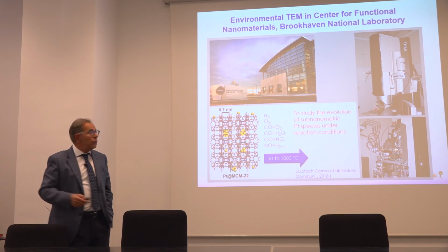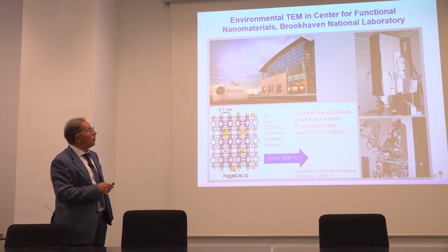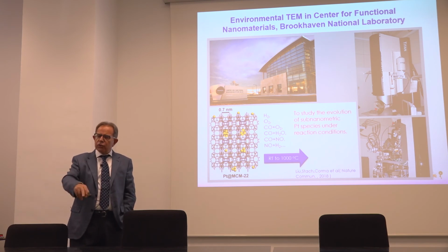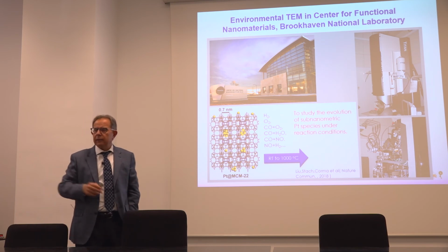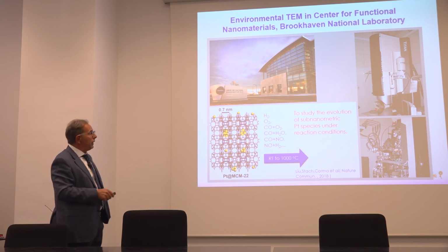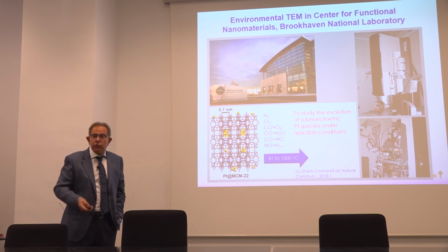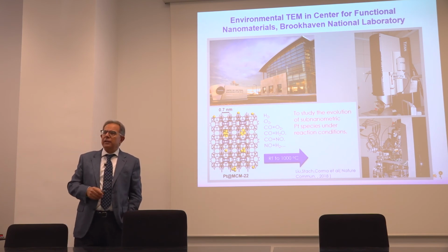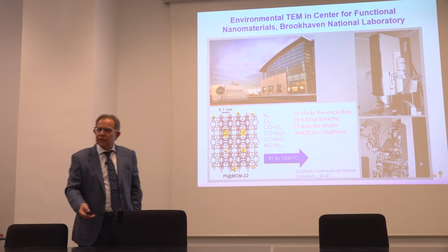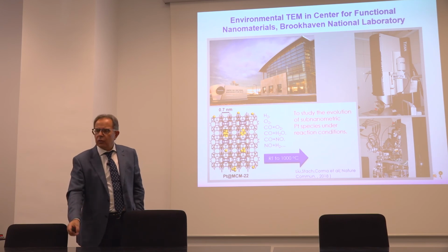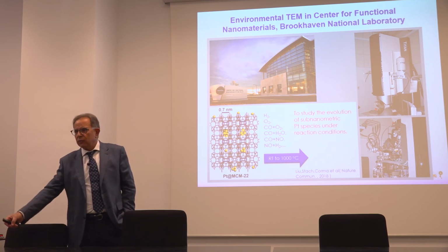So what we did was, in collaboration with the lab from Brookhaven National Laboratory, to look by microscopy at how those single atoms evolve during the reactions, either during treatments with oxygen and hydrogen, or during oxidation of CO, or water gas shift, or reduction of nitrogen oxide. And what we saw is that in many of those cases, the single atoms were migrating. They were migrating and getting agglomerated into clusters, and sometimes even further into nanoparticles.